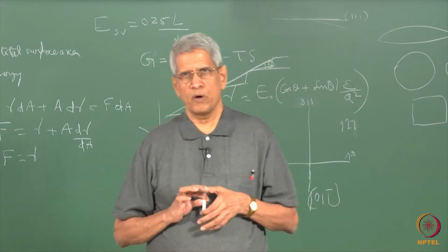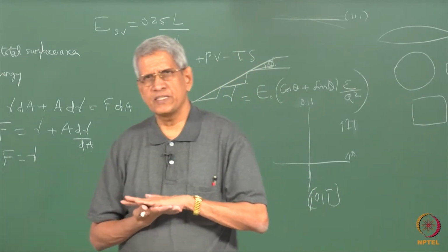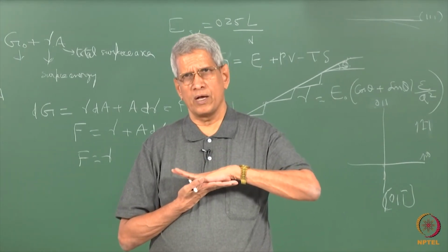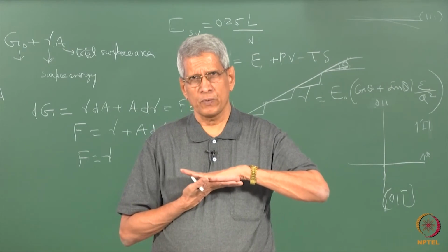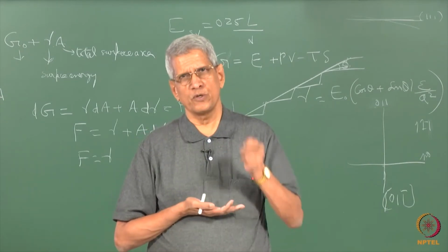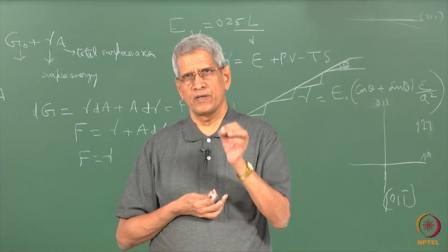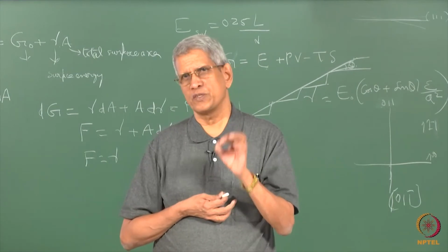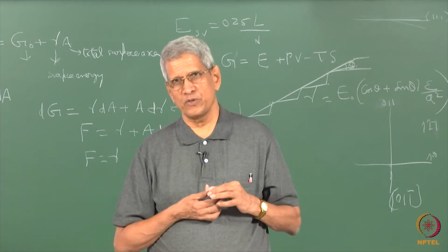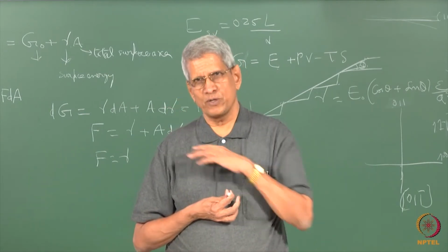Another way these boundaries are considered is, like the twin boundaries. A twin boundary in an FCC is on the one-one-one plane. There is no mismatch, it is a perfect matching. If you wanted to introduce a slight mismatch, we can do so by introducing some dislocations into these boundaries. Any boundary could be considered as made up of introducing dislocations. That is one model of a boundary, the dislocation model. Depending upon the number of dislocations we introduce into the boundary, the misorientations can change.